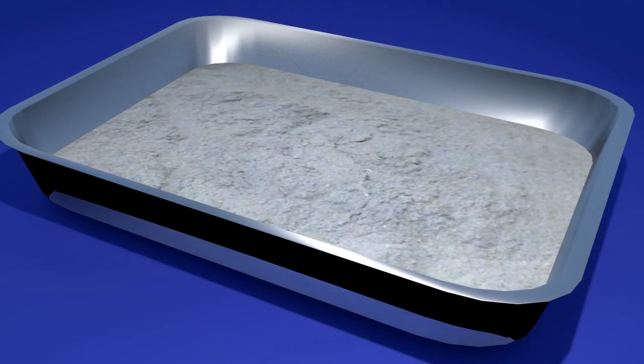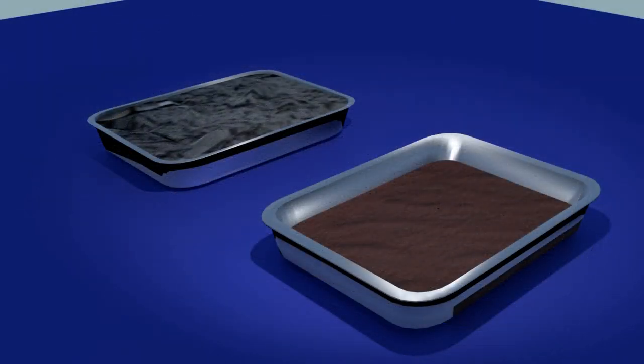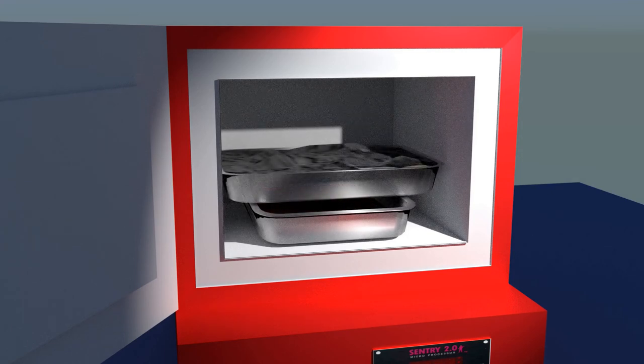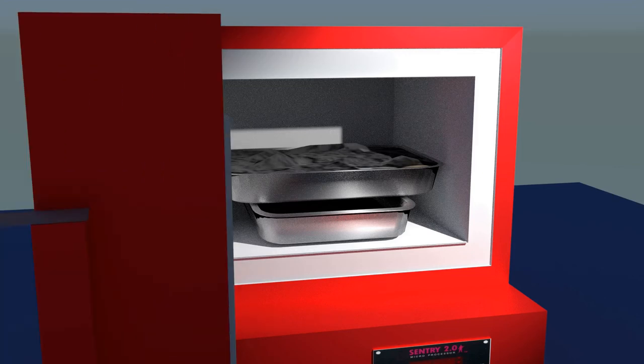The proper technique is not much different, but it is critical, and the results are very, very different. Place the sweeps in shallow steel or stoneware pans. The level of the sweeps should be no more than 1 to 2 inches for dense sweeps and no more than 4 to 5 inches for fluffy sweeps. Place the pans in your oven. You can stack them, but do not nest the pans. Make sure that the sweeps are fully exposed to the air. Leave the oven door slightly ajar. This is critical. The sweeps need a continuous source of air, without which thorough burning will not take place.